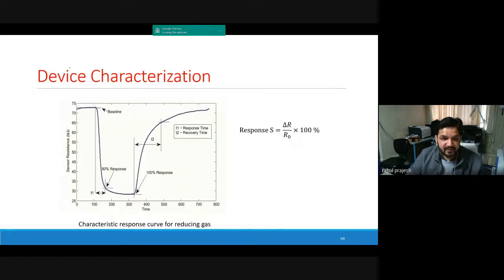Now this is the typical characteristic curve of the actual device which I have plotted. Now from here, I can tell you what you can extract. So it's the baseline of the device, which is basically the base resistance. Once you input the gas at this particular point, it goes down. So it's basically a reducing gas. If you remember the phenomena I told you, you have reducing gas and oxidizing gas. If you have reducing gas, the resistance will reduce. So the resistance drops suddenly, and then it saturates. The gas is continuously flowing and it saturates. The 90% of the saturation value is somewhere here.